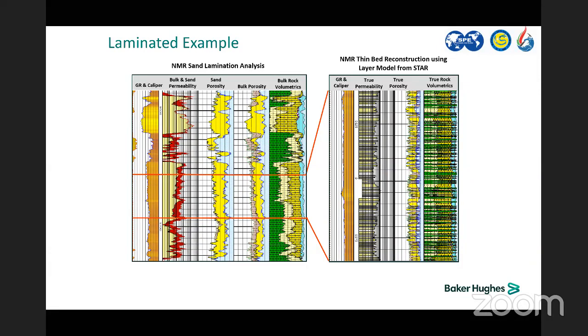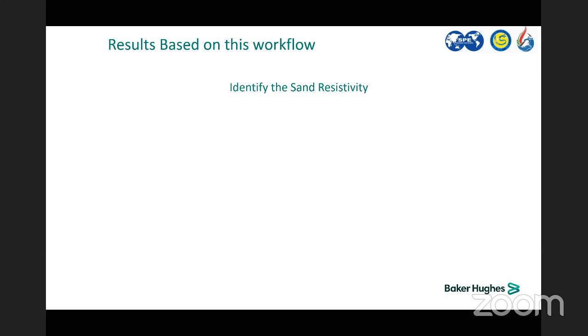So utilizing the layer model from the resistivity image will help you to get a high resolution model for your lamina. And this technique has been published. It's not new, but just like the change of introducing the dielectric and introducing the new NMR will help you to get much better. So each time we are moving a step closer to the real sand resistivity, sand permeability, sand porosity. This is the main approach and target for us.